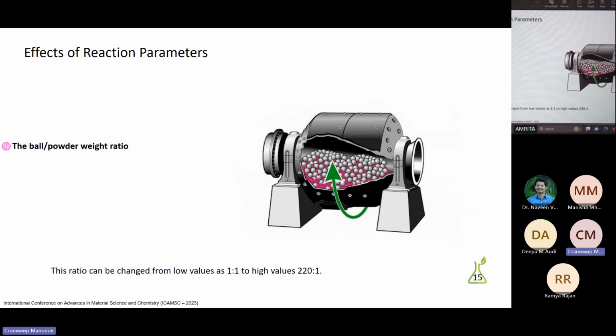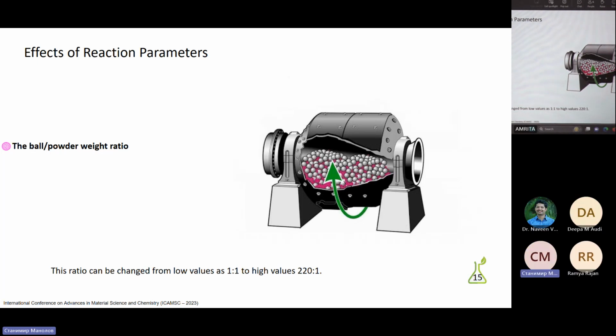The ball to powder weight ratio has been a crucial parameter as well that correlates with kinetics. This ratio can be changed from low values such as 1 to 1 to high values such as 220 to 1. At the high ratio, the number of collisions increases and more energy transfers, more heat originates, and so mechanical activation takes place much faster. By changing these parameters, novel materials that have desired physical, chemical, and optical properties have been produced.